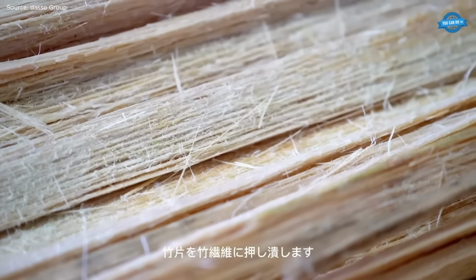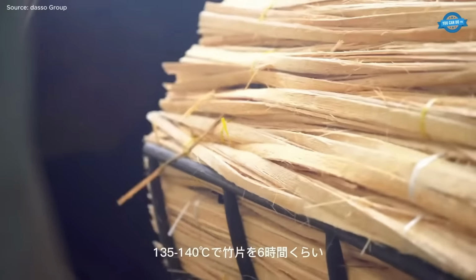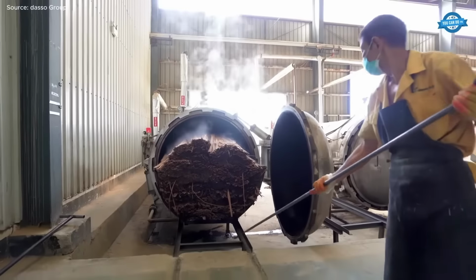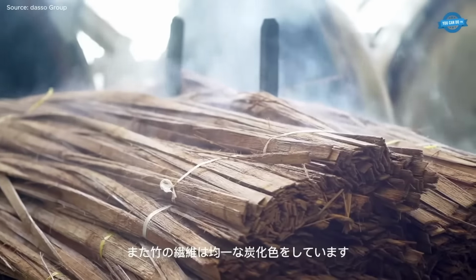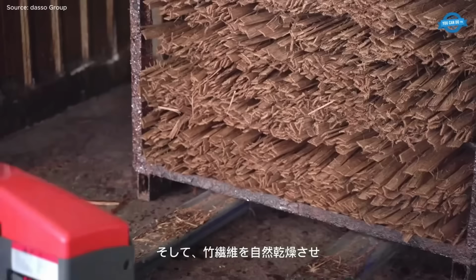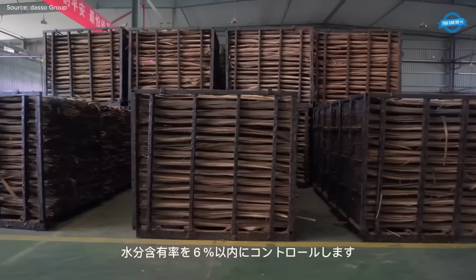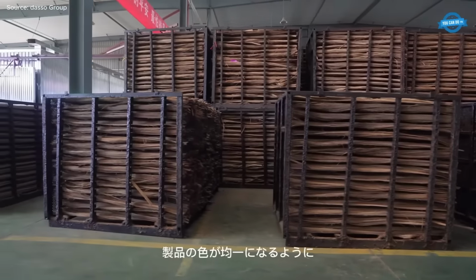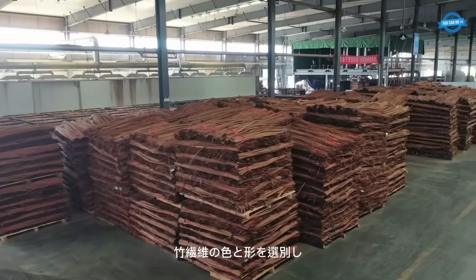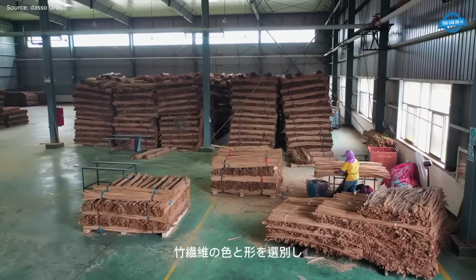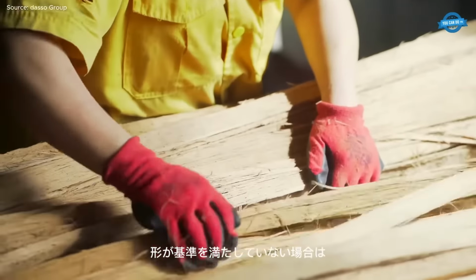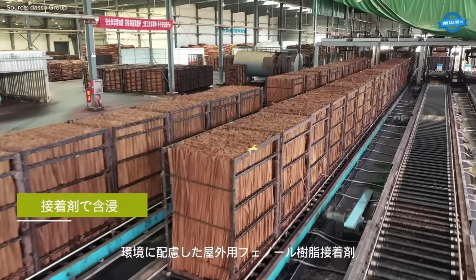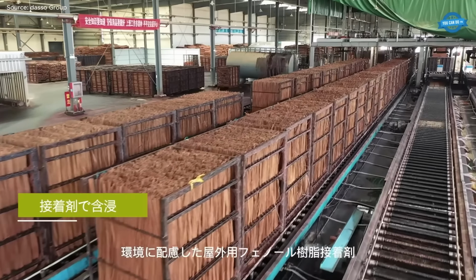Bamboo of varying diameters is split into uniform strips, with the outer skin and inner yellow layer removed. The material is then crushed into bamboo fibers and treated under high temperature and pressure, 135 to 140 degrees C, for approximately 6 hours, to eliminate insects and induce carbonization. This process produces fibers with a consistent, stable color.